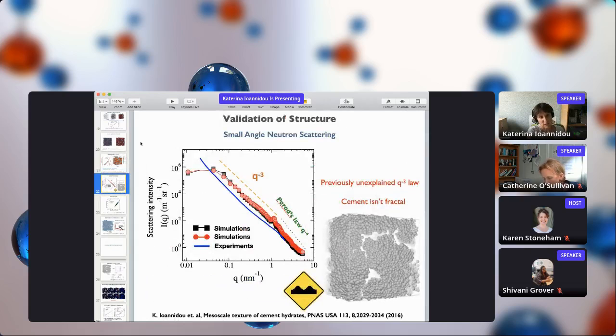One point of validation is the small angle neutron scattering. Here we see the comparison of the small angle neutron scattering signal calculated from experiments and from simulation, and we see that we have a very good agreement. We're also able to obtain a q to the minus 3 dependence, which is very characteristic for porous material of cement. We're able to provide an explanation for this, which is due to the surface roughness observed on this material because of particle polydispersity and because of this type of aggregation procedure, which is very fast out of equilibrium. So we have the creation of these clusters that give a surface roughness at 2 different orders of magnitude.